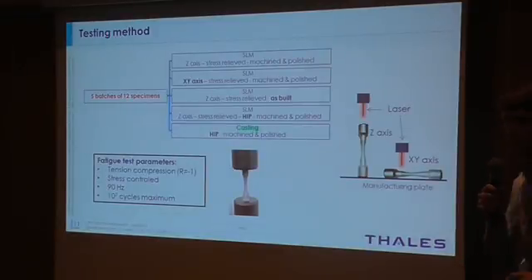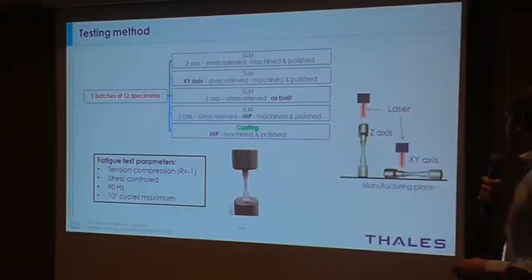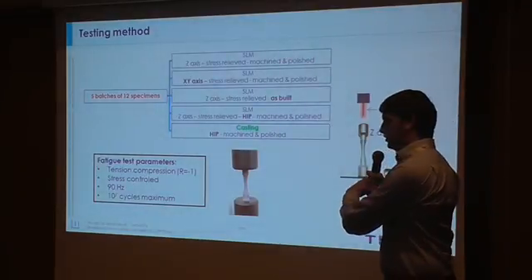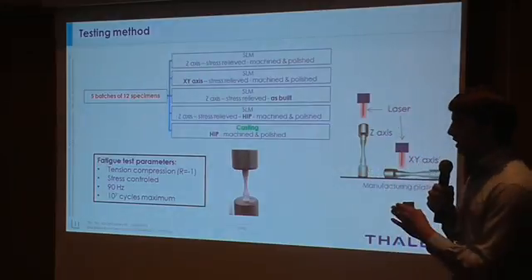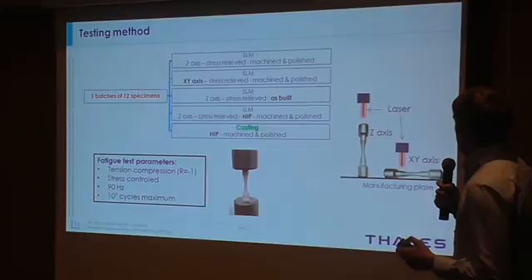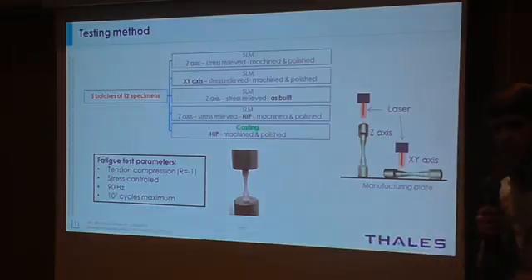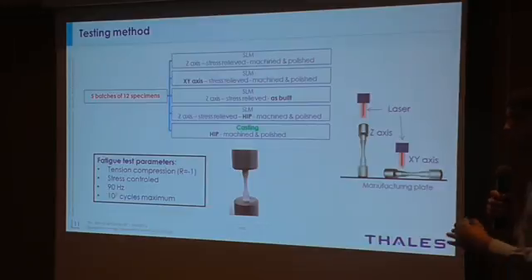So, a little slide on the testing method. We performed some high cycle fatigue tests. So here are the parameters, and we had 5 batches of 12 specimens, and we built them in order to evaluate the 3 parameters. So there are some specimens which were built in the z-axis and other in the x-y axis. Some specimens were machined and polished, others were left as built. And some specimens were stress relieved, and others had an HIP heat treatment. And then we compared with casted HIP specimens to compare with the conventional processes.